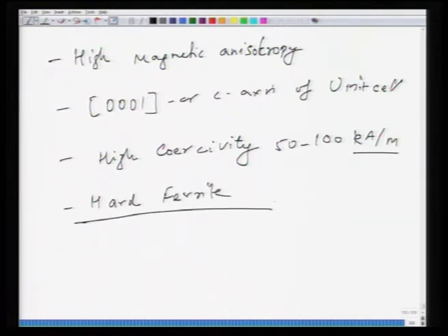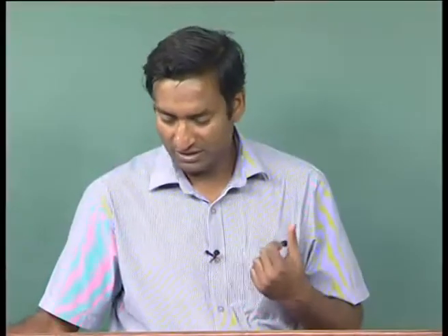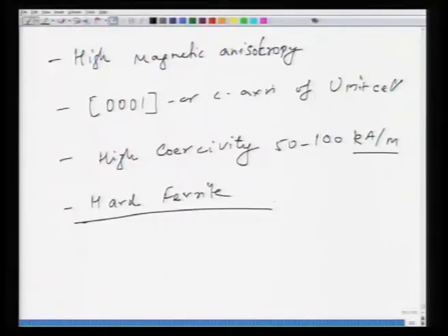So, essentially barium ferrite is a hexagonal material with a large number of atoms, two formula units per unit cell, making up the hexagonal unit cell, which is essentially based upon the iron oxide structure, Fe2O3, hexagonal iron oxide structure, and this contains ions in such a position that it gives you a very large magnetic moment per unit cell, of the order of 40 Bohr magneton. So, this is a large number. Now, what we are going to next take up is essentially the case of garnets.